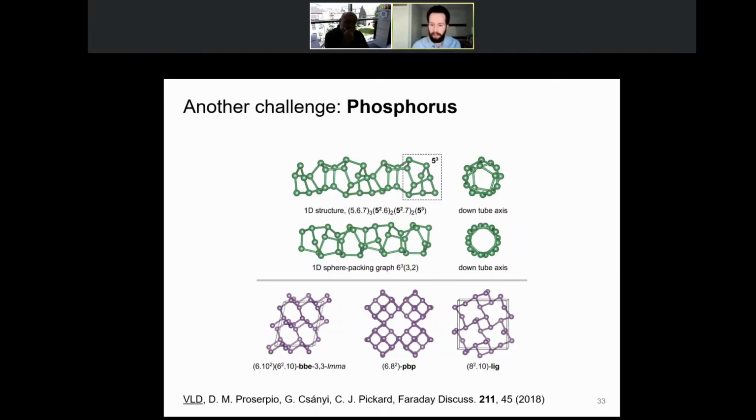There are a few predicted 3D structures here, so the chemists will recognize this one here is the same anion network as in lithium germanide. So according to the Zintl-Klemm rules, you'd have this kind of network in the 3D structure, and that fits quite well with what we expect. You can do much more with these potentials.